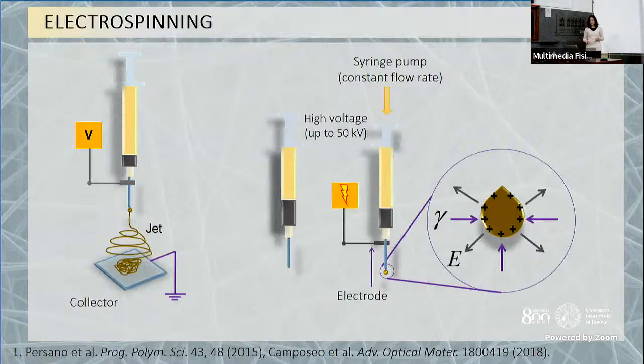What happens is that when you start feeding your solution, a drop is ejected from the needle, and once the electric field is applied, this drop experiences many forces. There are surface tension and viscoelasticity that keep the drop in its initial shape, but when the electric field overcomes a certain threshold, the drop starts to deform, and after deformation, when you still increase the field, the polymer is ejected in the form of a jet from the needle, as you can see here. In the time of flight between the needle and the collector, the jet experiences high stretching forces, but also the solvent within the solution starts to evaporate. This allows one to collect nanofibers in the solid state on the collector.